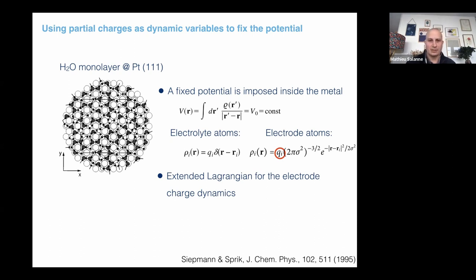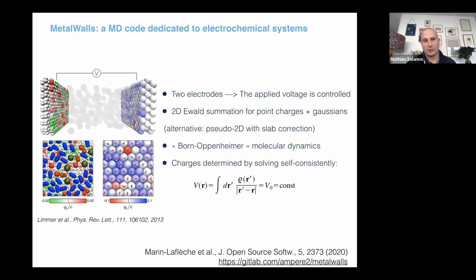So then this work was left out, I would say, for quite a long time until Paul Madden started to work on it and to adapt it to the case of electrochemical systems. And then we did the follow-up in my group. So the main change was to apply this to two electrodes. So in that case, we don't fix the voltage inside a single electrode, but we fix the difference of potential between the two.